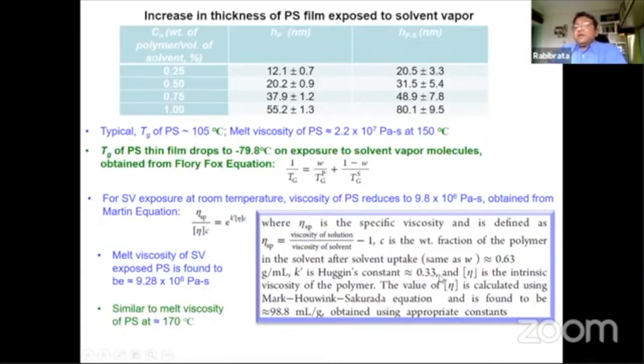So while working on this, particularly the rebuttal of this paper, we actually learned a lot of stuff. We learned about the Huggins constant and Martin equation, etc. And here came the real surprise for us. From the literature, you can see that at 105°C or just above the glass transition, so sorry, this is not 105, this is 150, I guess. Yeah, right. So Tg is 105, so this is around 150. The temperature at which we did the thermal annealing of the films, the melt viscosity is 2.2 times 10 to the power 7 Pascal second, which is great. And upon calculation, we found that for the solvent vapor annealed samples, the melt viscosity is 9.8 times 10 to the power 6 Pascal second.